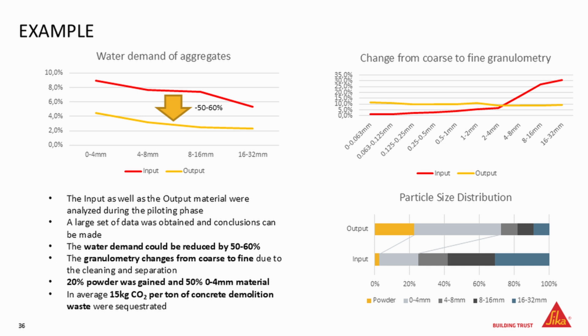Then in the pilot plant, we did the combined step 1 and step 2. We put the CO2 in the process, and there, on average, we could sequester 15 kilograms of CO2 per ton of concrete demolition waste during all these trials that we did. That is also an important figure.